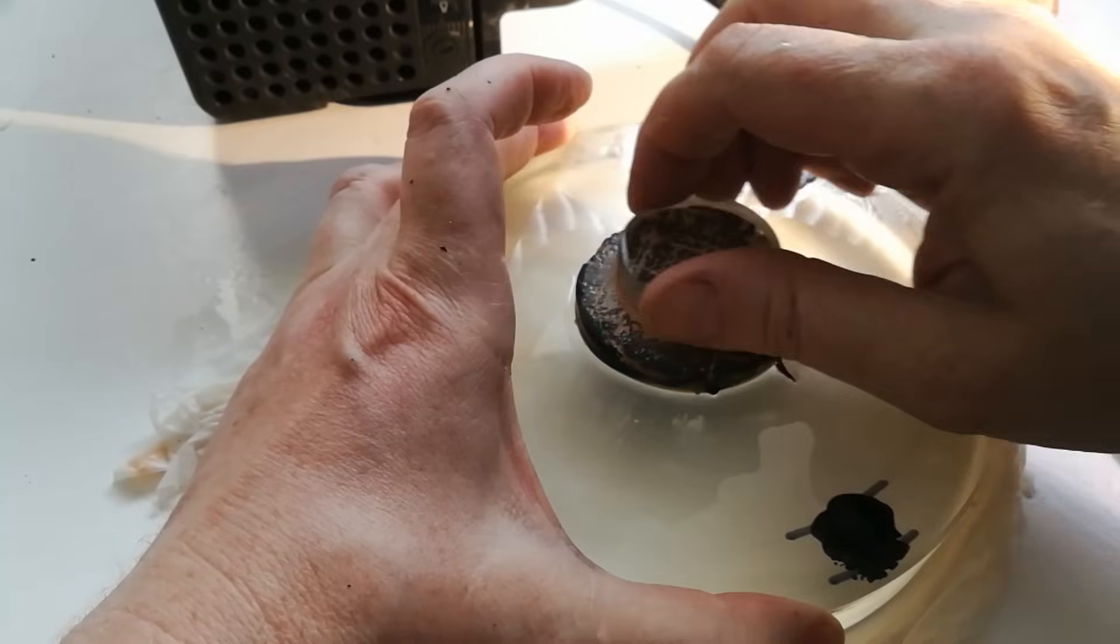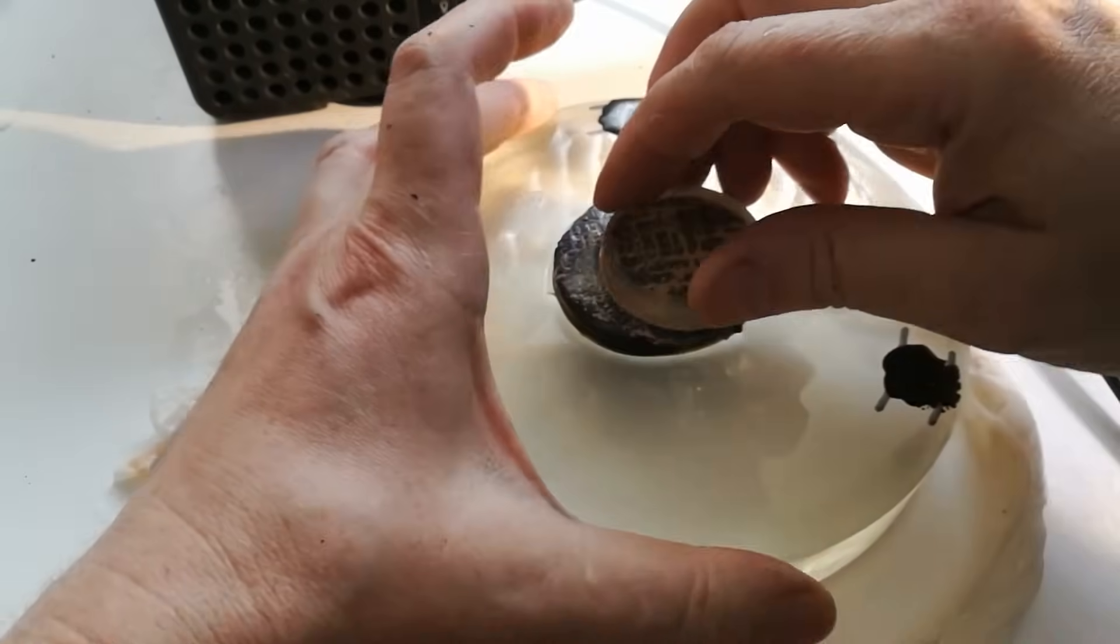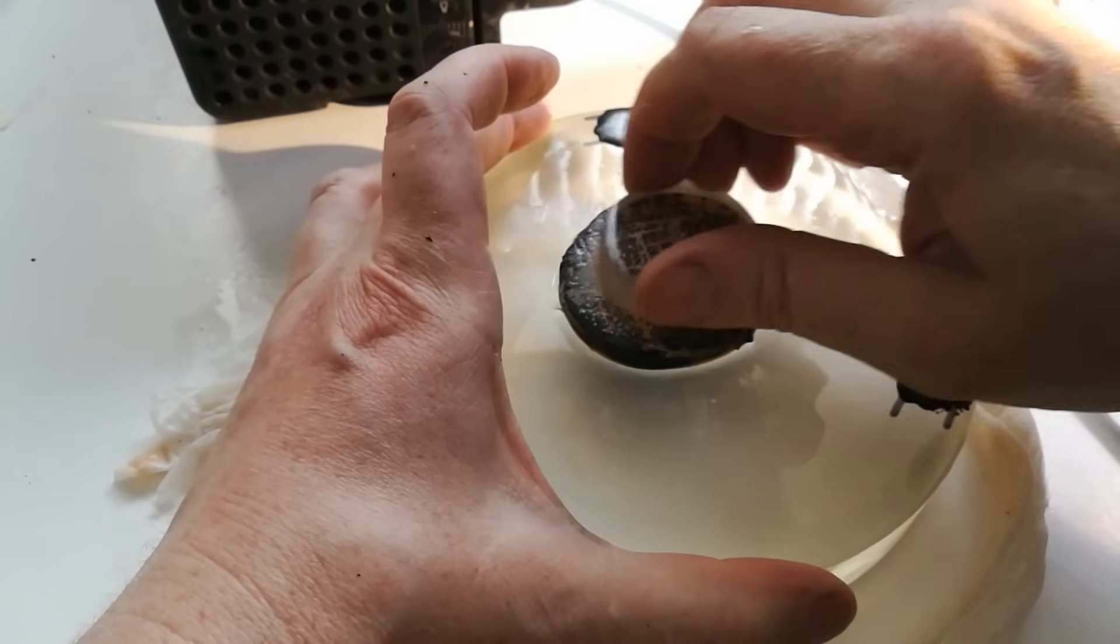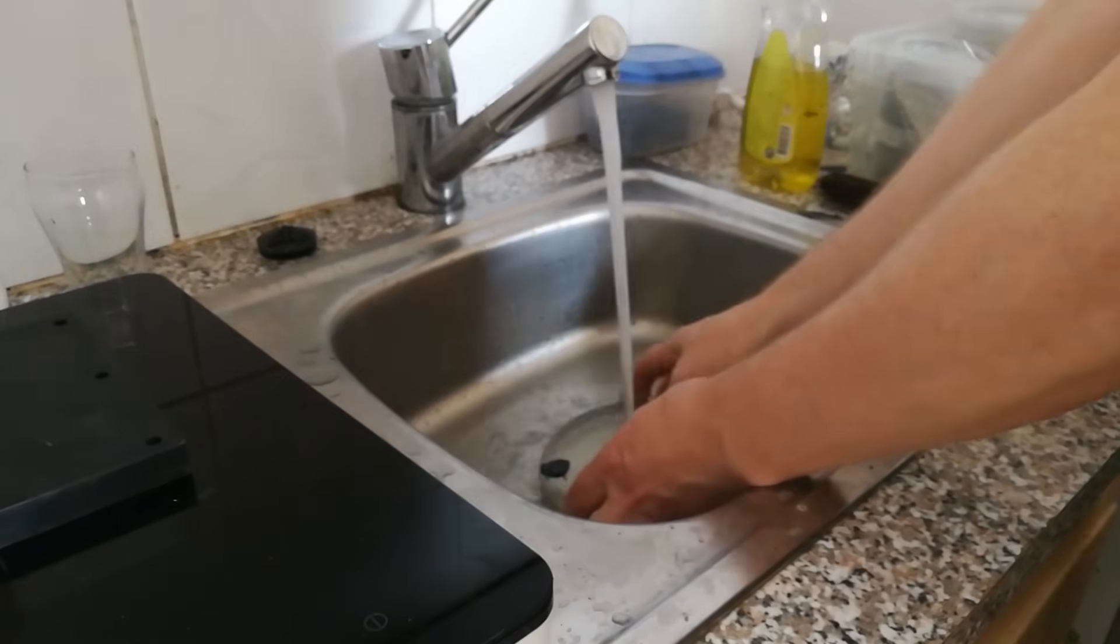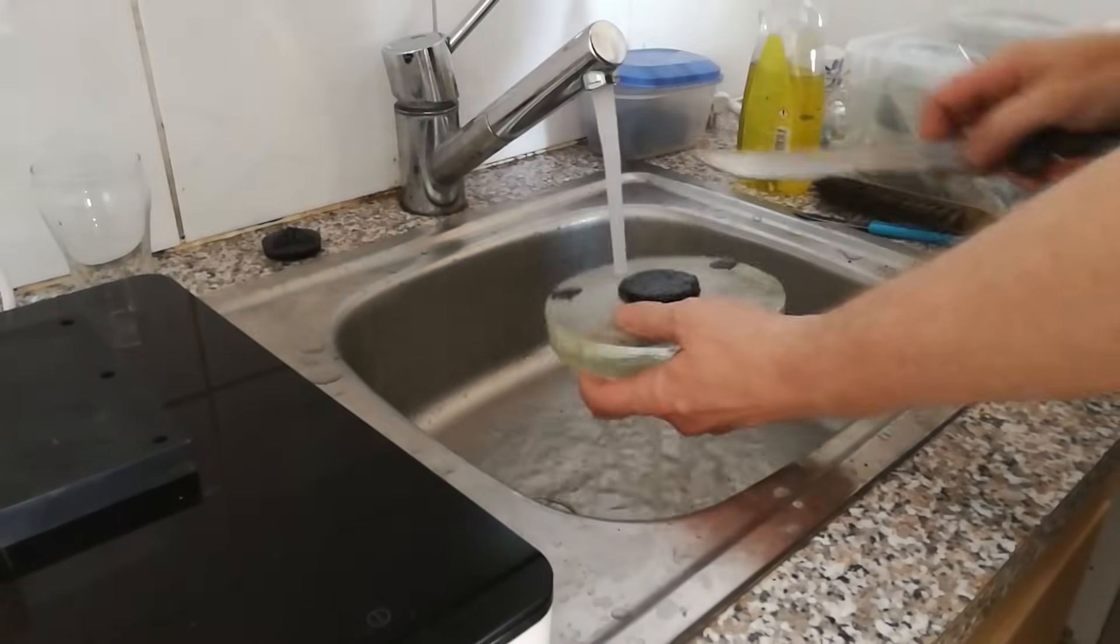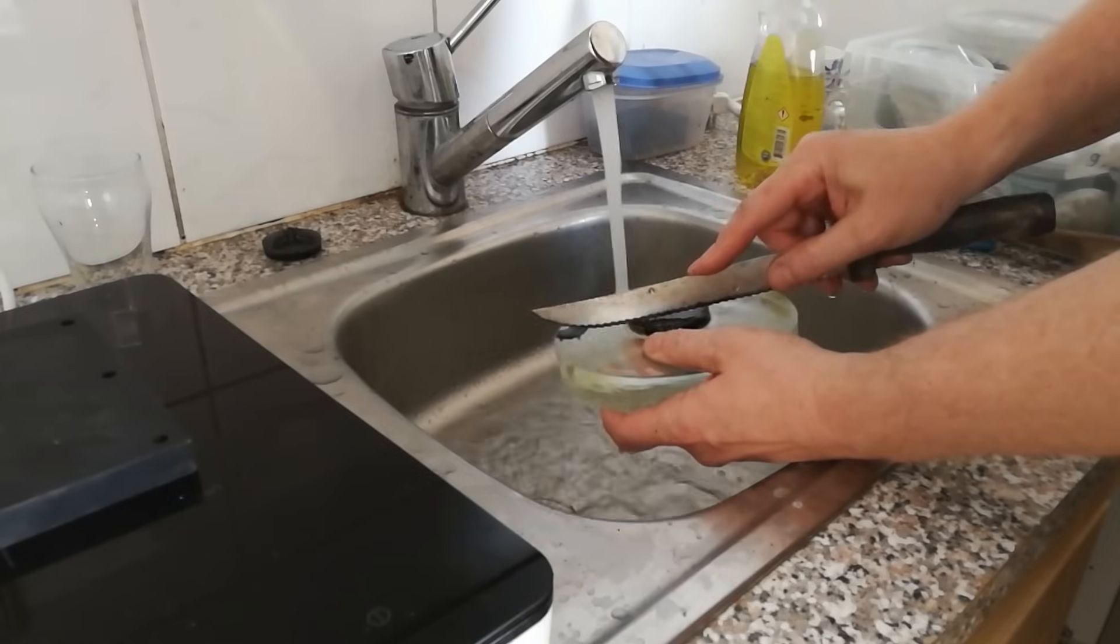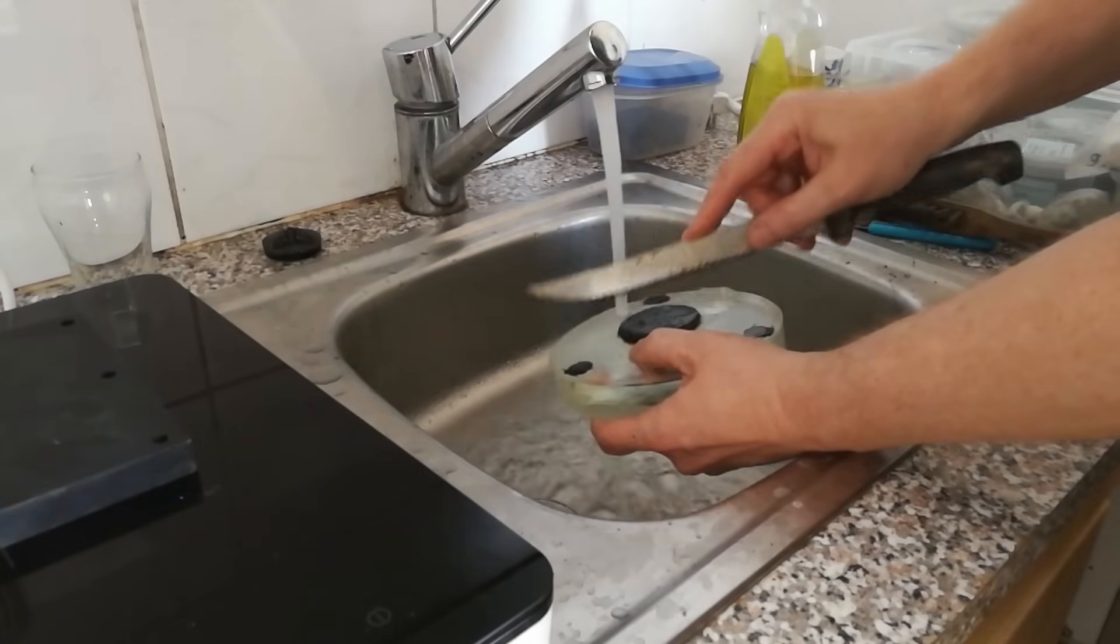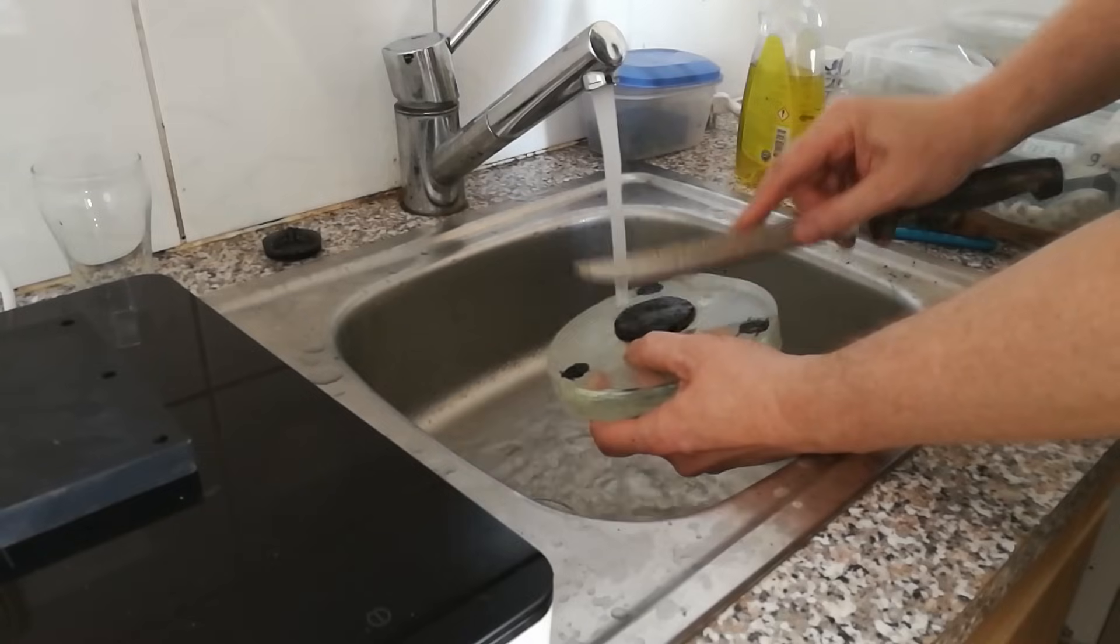Another source of heat is warm hands. This local heating can be an additional problem when keeping the mirror shape constant. During the whole polishing process, the pitch should retain its open structure and should be opened again using a knife or a steel brush when the channels in the pitch fill up. The channels also function as a drain for glass particles that are removed from the surface.